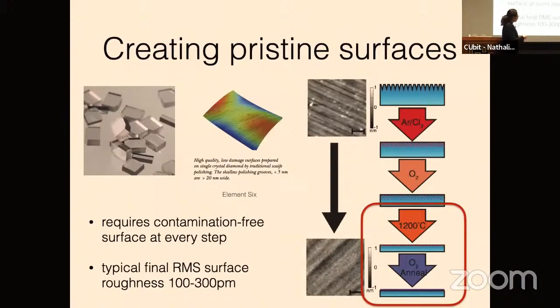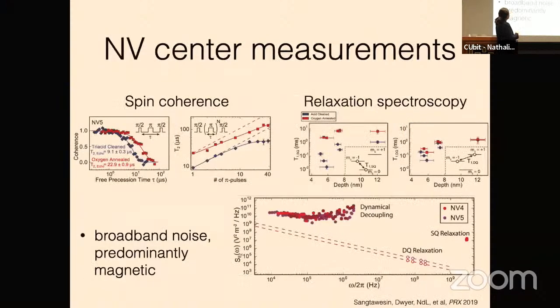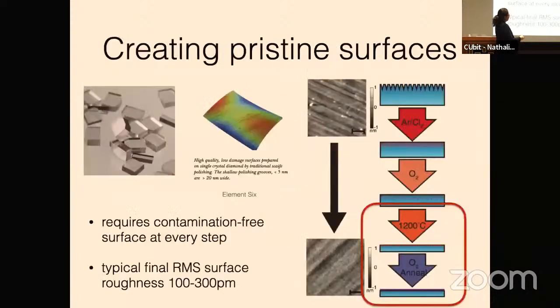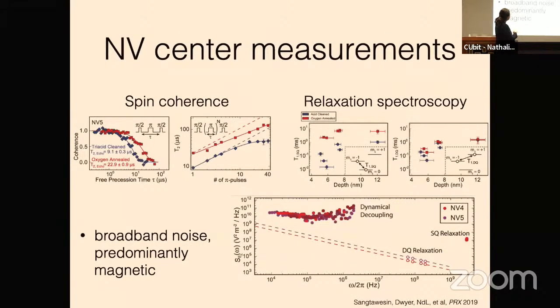So we can do a little bit more to understand this by zeroing in on the comparison between these last two steps, okay? I'm going to call this the acid clean surface and the oxygen annealed surface. If I look at NV spin coherence between these two surfaces, you can see that the Hahn echo T2 gets increased by about a factor of 2 or 3 with this last step. We can also do dynamical decoupling to probe what the frequency of this noise bath looks like, and we can see that we get this improvement across a very broad bandwidth.